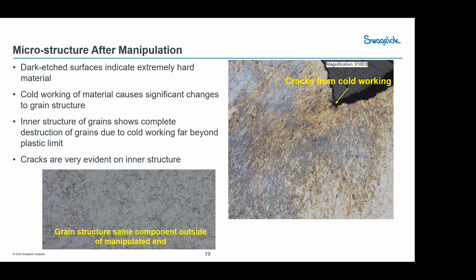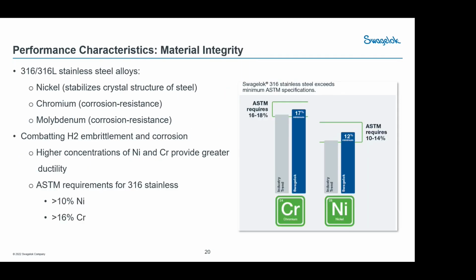So putting cracks into your system before you've induced them or forced it to happen in another way is really not a good thing. Will this fail in your lab, in the lab condition as you're qualifying a system? No, probably not. Hydrogen won't get it that fast. It will happen sooner in the field, and that's really just going to depend on the conditions. So introducing cracks into materials right off the gate is not a good thing. So it's just something to be careful about. If you're looking into manipulated end fittings, you got to watch out for it.